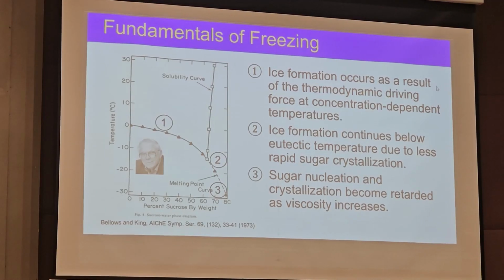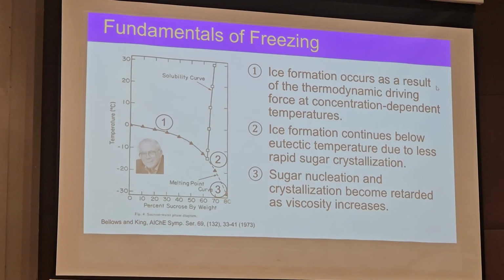So, if we look at freezing of water in food materials, we could look at also the work that was carried out in the early 70s by Professor Charles King in Berkeley, and they did quite a lot of fundamental work in understanding how the viscosity of a solution changed when it was getting frozen, and they described actually that there's an amorphous phase form and that it becomes stiff at some point. So there was ice formation because of thermodynamics, and then the ice formation continues even below eutectic temperature. So not the solvent crystallizing quite often, because sugar crystallization is a slow process. The water molecules crystallize much easier, but very slowly also if the viscosity is very, very strong.